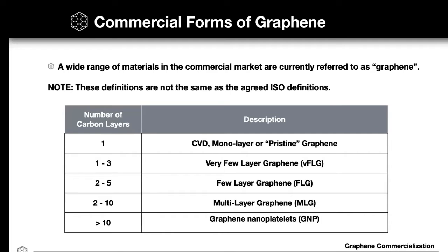Now, when we refer to graphene, I just want to make sure that everybody understands that there are different types and forms of graphene. We're talking about CVD or monolayer graphene, which is literally a single atomic layer of sp2 bonded carbon in a crystalline structure. And then there are different types of graphene that are recognized under the ISO standard, which includes up to and including 10 layers of carbon. And so you have everything in between in terms of the number of layers. And then you can also differentiate graphene materials by the lateral size, the width and length of those flakes, if you will, or those crystals. Can differentiate from sub 1 micron to multiple microns in lateral dimension.